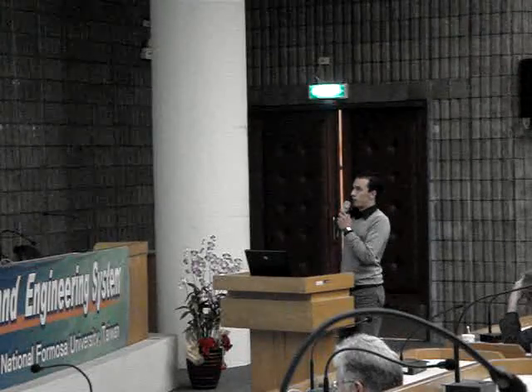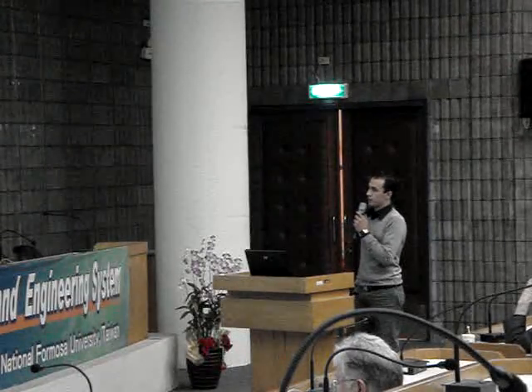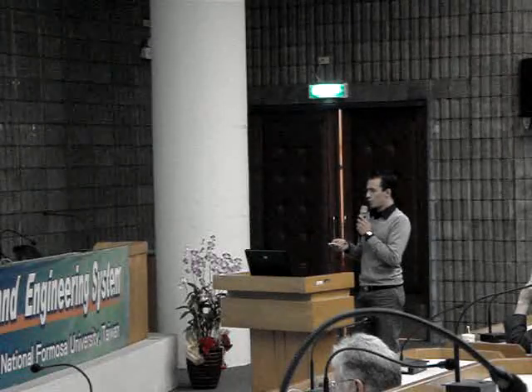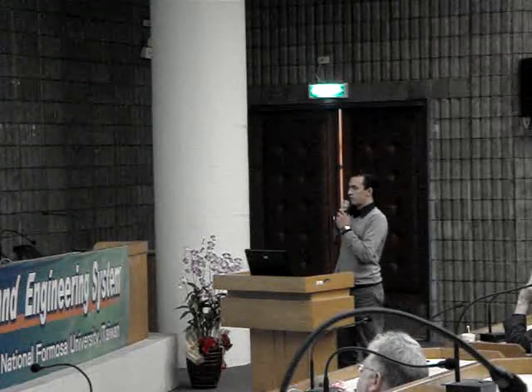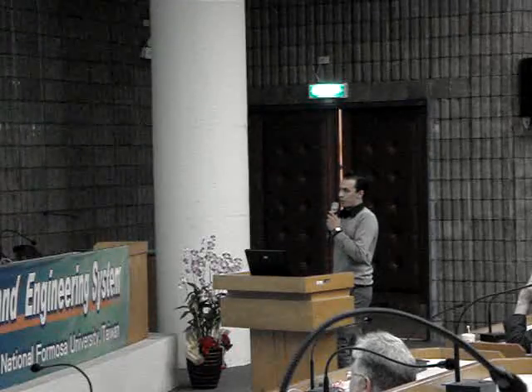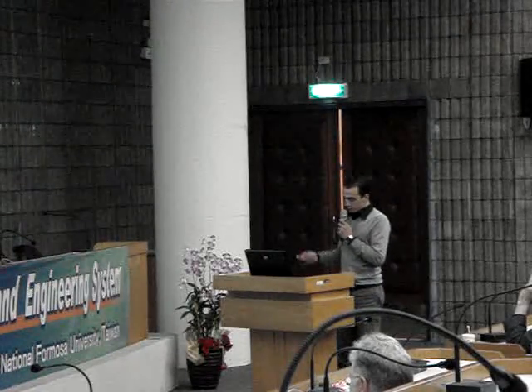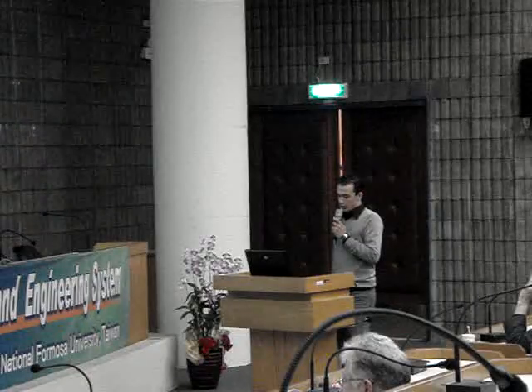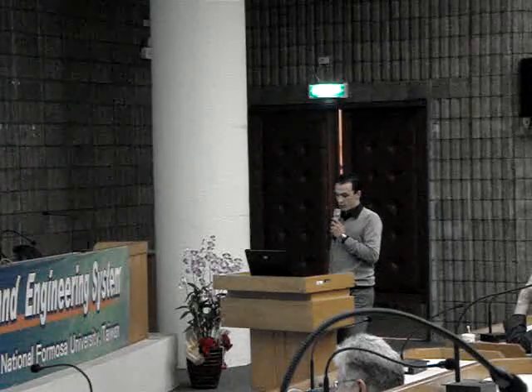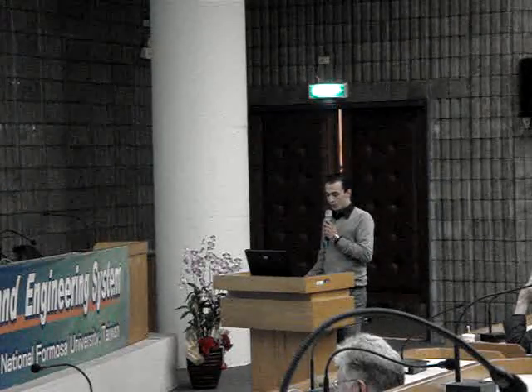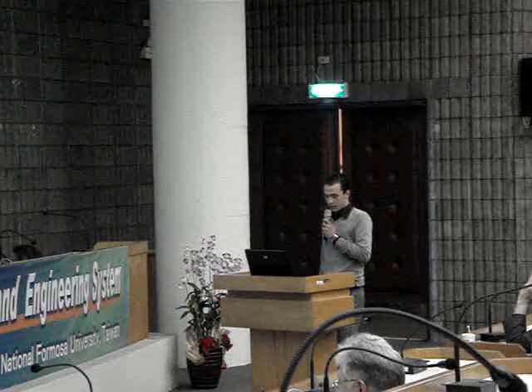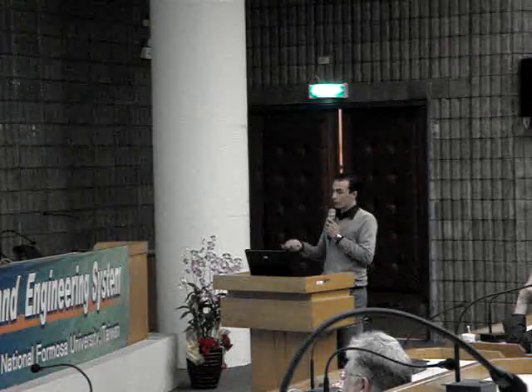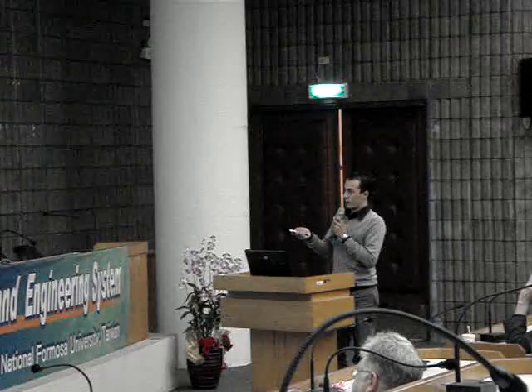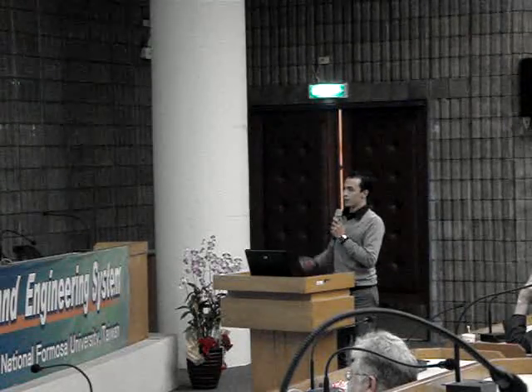Result and discussion: the microstructure and characteristics. In this picture, we can see the micromorphology of atomized SnBi alloy particles by SEM. It shows that the particles were obtained from the spray gun with an air pressure of 96 kilopascal and a spray distance of 450 millimeter. It is clear that the optimized particle diameter varies from 2 to 10 micrometer, because our scale bar is just 20 micrometer.